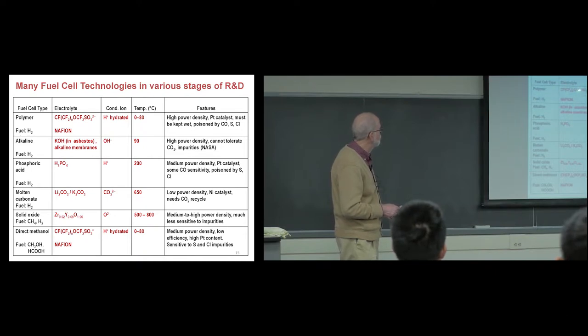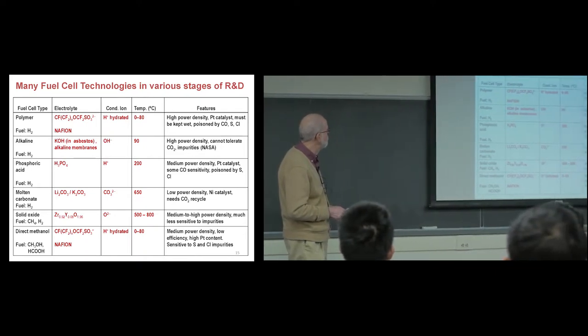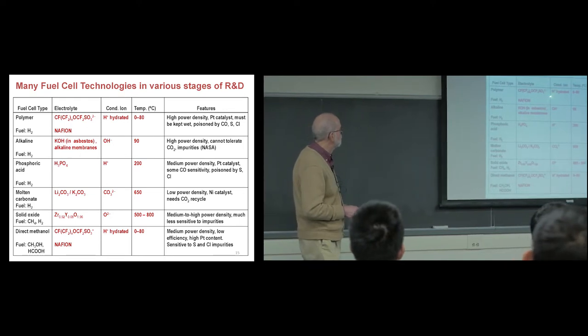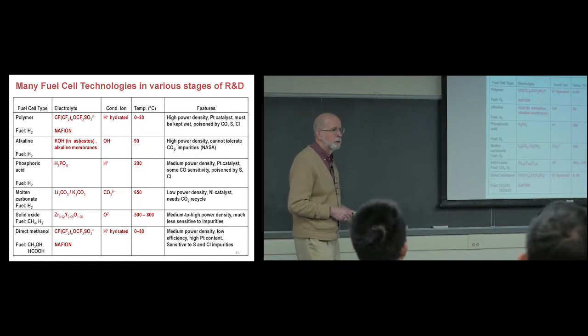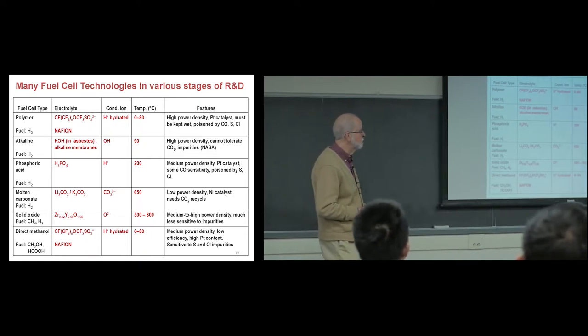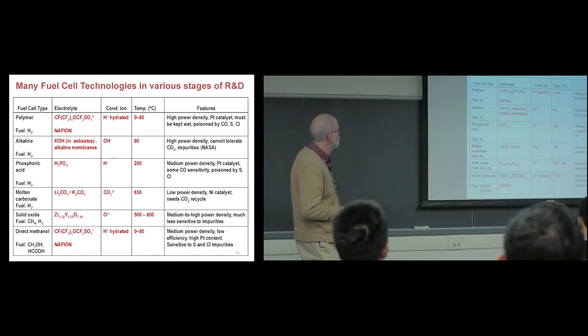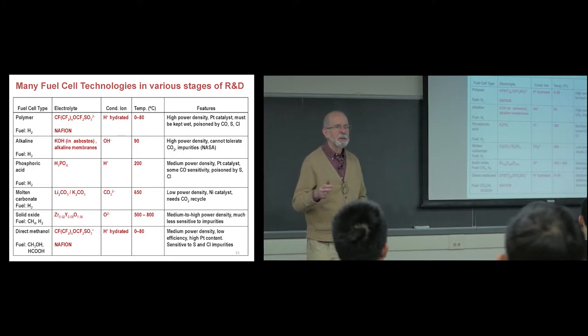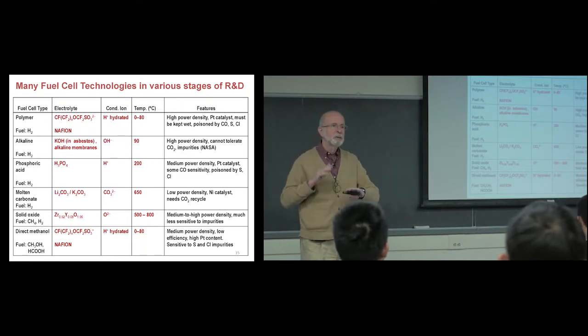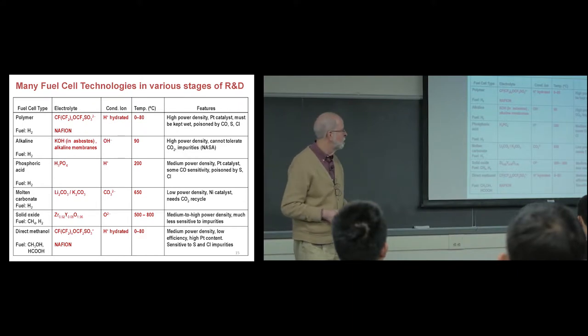This is the chemical formula for this stuff. It's a polymer called Nafion. And what's moving through it is H plus hydrated, and it operates well in the range between 0 and 80 C. Very nice. That's about where we would like it to be. Turns out that you have to be a little careful, because if you take in fuels that are contaminating, that is, they carry something else in like sulfur, that will poison the platinum catalyst. What it means is it reacts with the surface so that the hydrogen can't get at it, and it can't take it off, and you kill it.